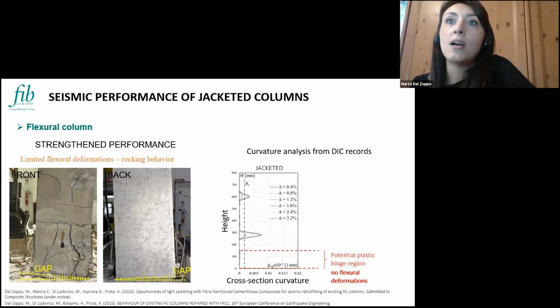And these peaks that we are observing in the plot are actually false curvature peaks that correspond to the opening of the cracks in the jacket that we observed during the test. So basically, they are rigid rotations around the cracks developed in the jacket. This is important when we need to model the behavior of such an element: all the assumptions that we usually make about the plastic hinge approach are not valid for such kinds of elements, but need to be further investigated.